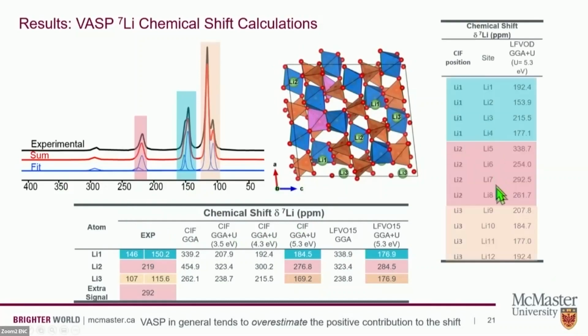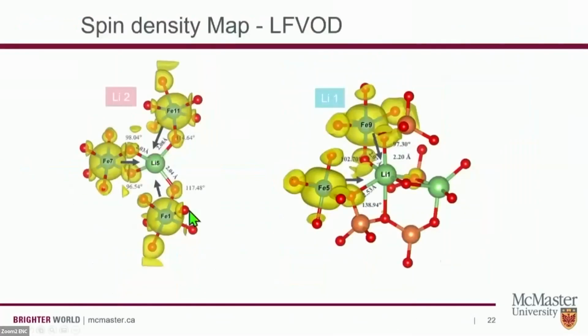So there's 3 groupings of the chemical shift. Each lithium is now split into 4 positions. There's one particular shift of the lithium-2 that's jumped out to above 300 ppm. And what does that shift represent? Well, it represents a different local environment for that lithium where there's more donation from the iron unpaired electron density into that lithium center. And this is just a visual for you of that.